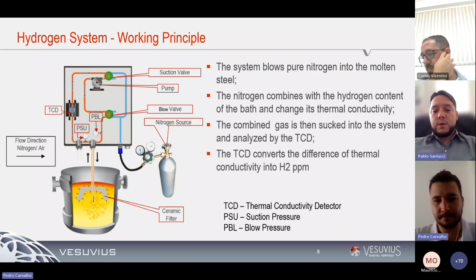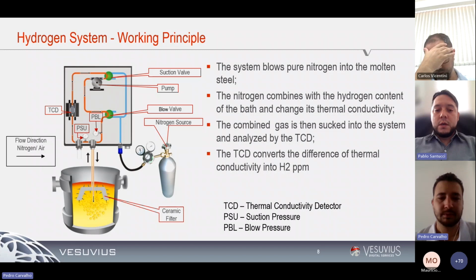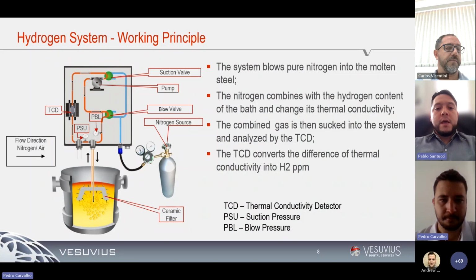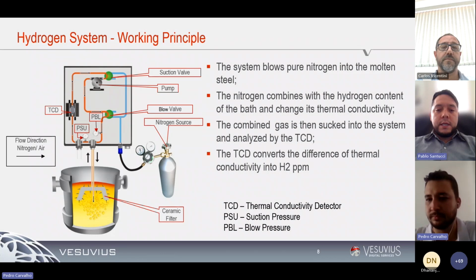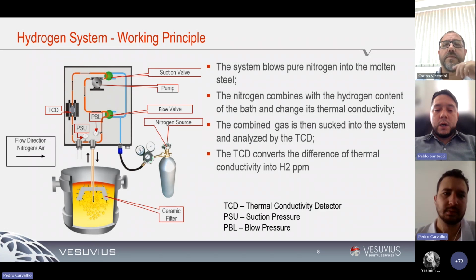By the time our system starts purging inert gas, in this case nitrogen, through its channels, because we have two different channels, one goes toward the molten steel and purges nitrogen inside. That being said, this nitrogen will be combined with the gas inside of the steel, and then this gas from the steel can be sucked in by our ceramic bell, which is built into our probe. It is then filtered and its thermal conductivity is measured.